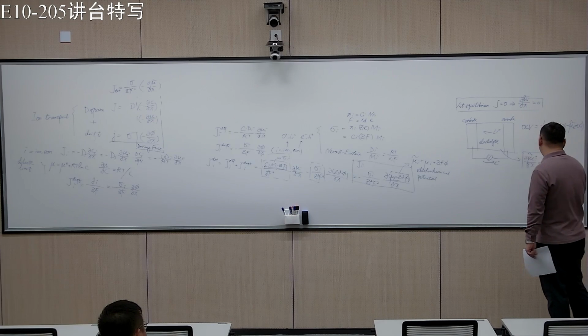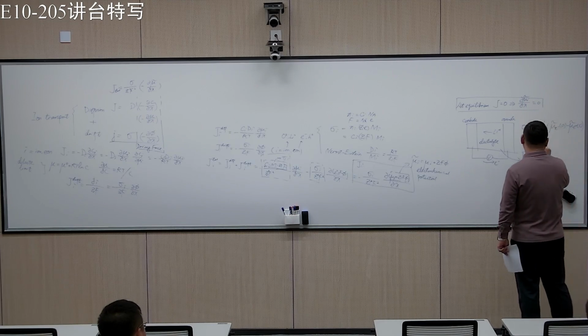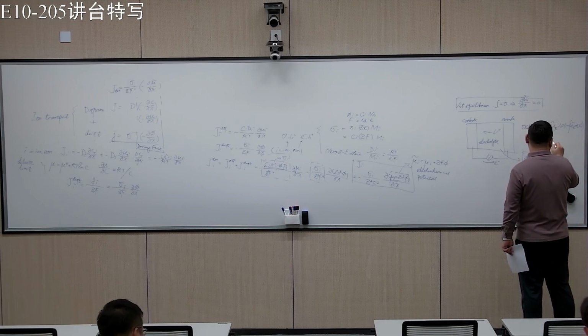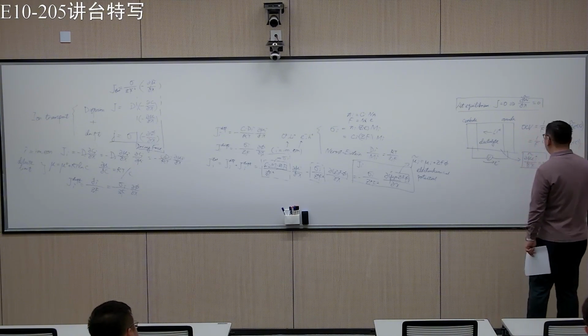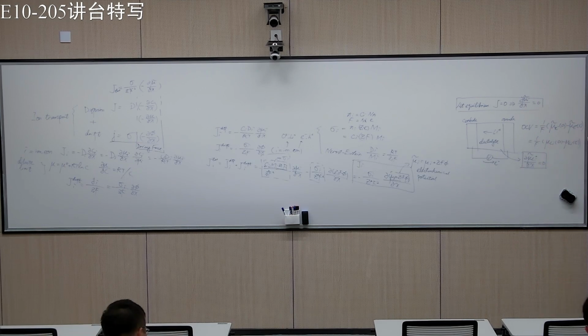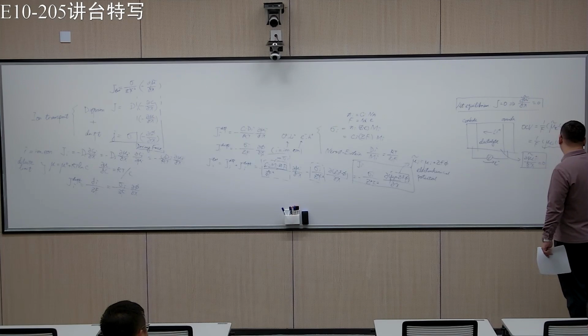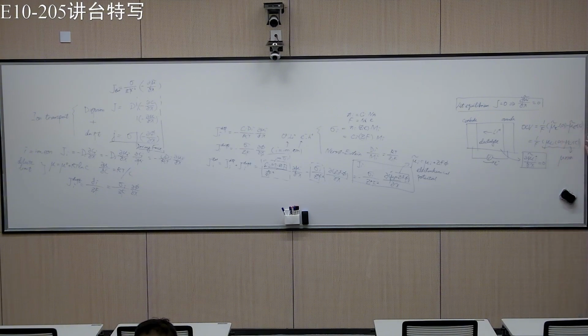However, if we apply this, and last lecture we showed that this can be directly related to the chemical potential of lithium. So this is the charge neutral species of lithium in the cathode and in the anode. Okay, and of course you can link that into the reaction chemical potential or Gibbs free energy of reaction per mole.